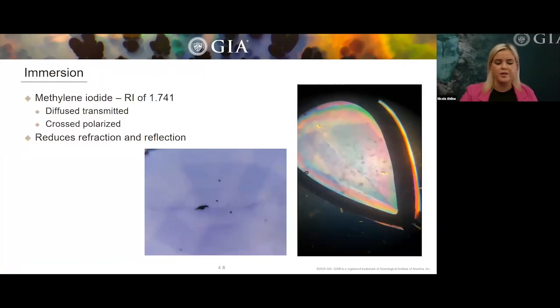So another tool that a preliminary gemologist might use is immersion. In GIA laboratories, they commonly use methylene iodide, which is toxic and should always be used with caution when handling it. Methylene iodide has a refractive index of 1.741, which is very close to the refractive index of corundum, 1.762. That's because corundum is the most commonly immersed stone at the laboratory.